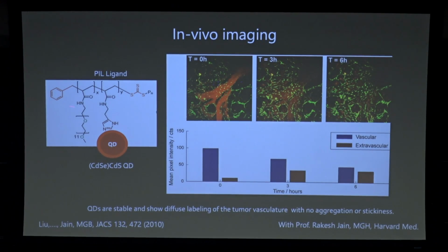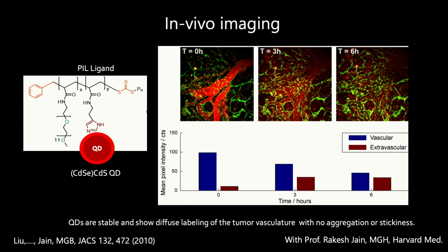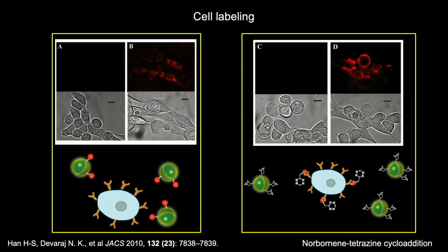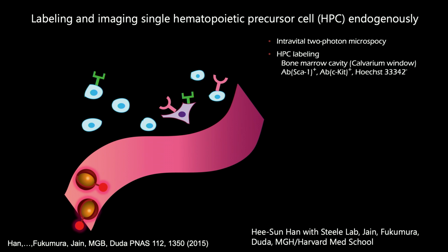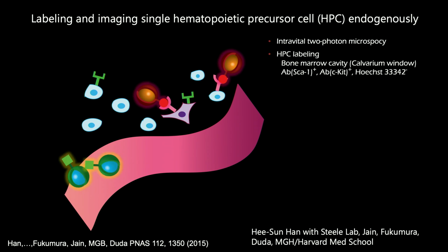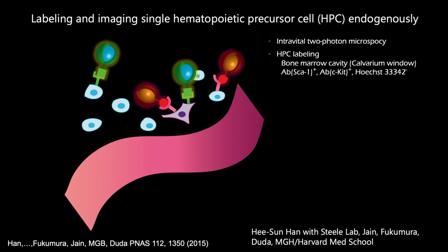We worked hard on surface chemistry to make these compatible with the in vivo environment. This is an injection of quantum dots in the mouse again. You can see the quantum dots sort of diffusing out of the vasculature without aggregating. We worked hard on how to conjugate the quantum dots to the outside of the cells using bioorthogonal chemistry. This is an in vivo experiment here with the Jain group where we labeled with 2 color dots to label these very rare cells in the bone marrow. And so we start with the red dots and then the green dots, and only these very rare cells have the 2 receptors on them and the absence of a blue stained nucleus.